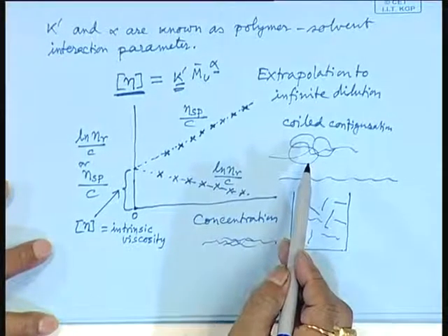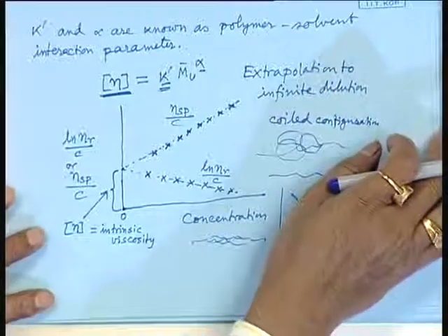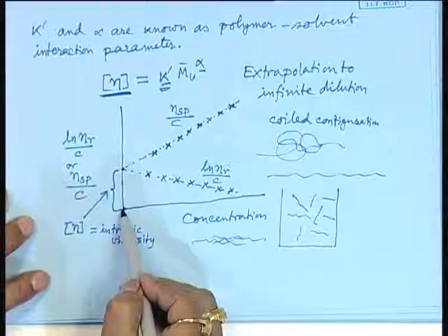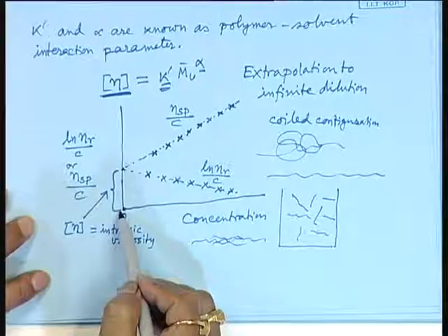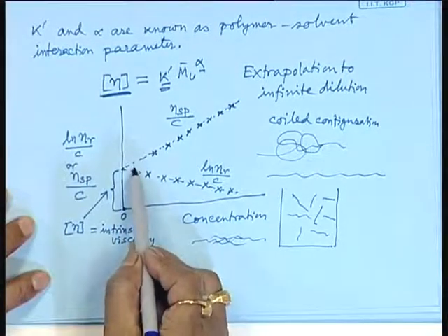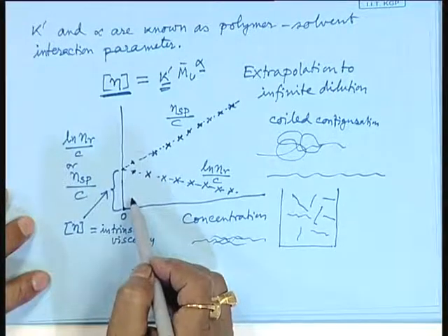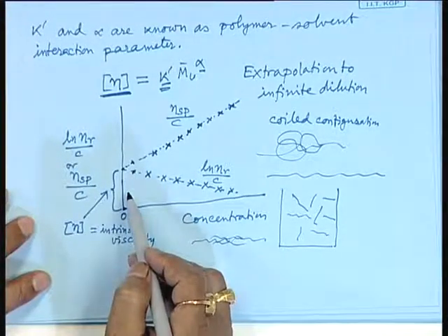That is why when we like to measure the molecular weight by viscosity measurement, we have to go for higher dilution or extrapolation to zero concentration, infinite dilution. But at these regions the flow times for the solvent and the solution are very close, and you cannot distinguish.